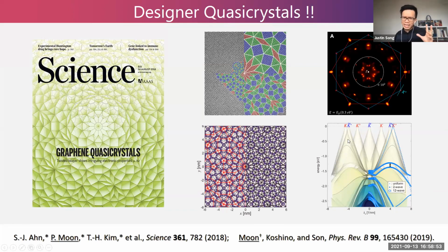But then what does that even mean in the case where you don't even have any true crystalline periodicity? Would you maybe have something about that? Actually, this is the band structure of the twisted graphene quasi-crystal. Such a plot is possible because at most points, the two graphene layers are almost decoupled, and the strong interaction occurs at a specific wave vector. Here I plot it as 0, and there the resonance coupling occurs. At other points, it smoothly varies to the decoupled structure.